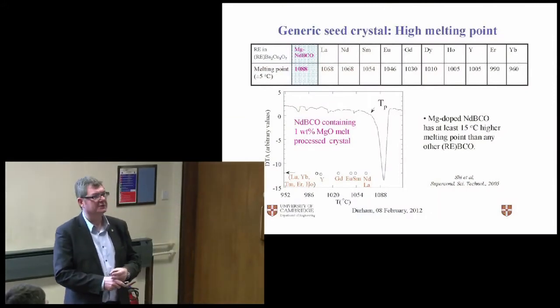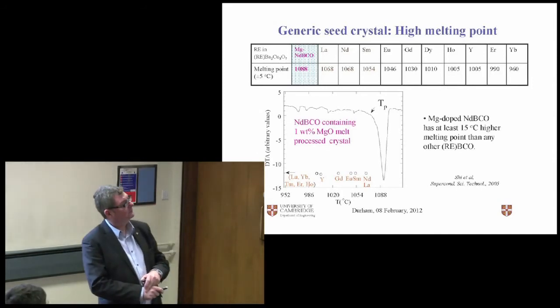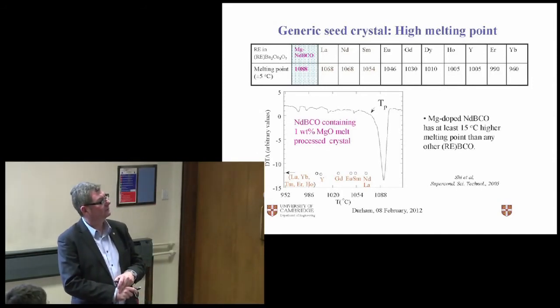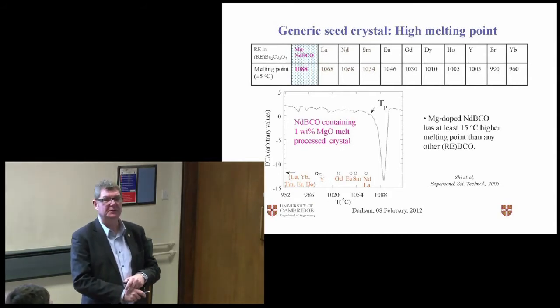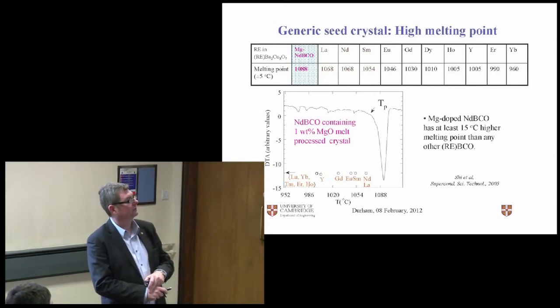But this generic seed crystal was discovered during her PhD. She tried a number of compositions, but she found that if she doped neodymium barium copper oxide with magnesium, you get this large increase, 20 degrees, in decomposition temperature.